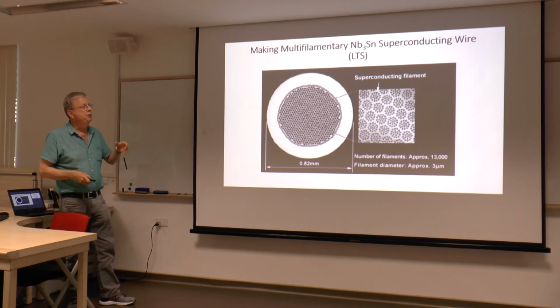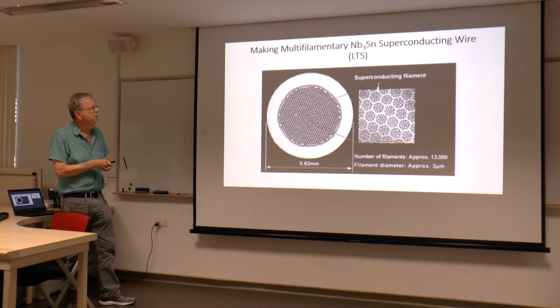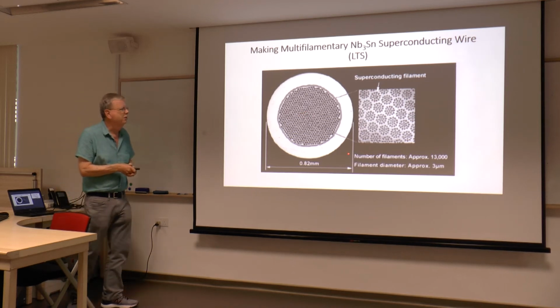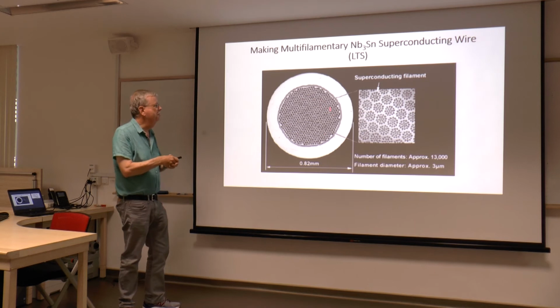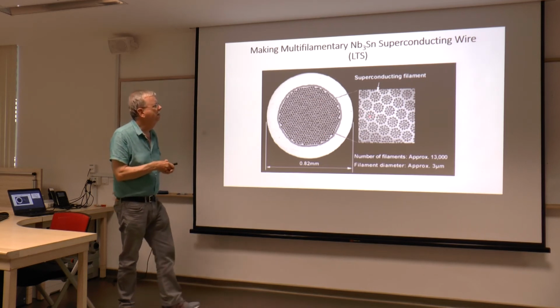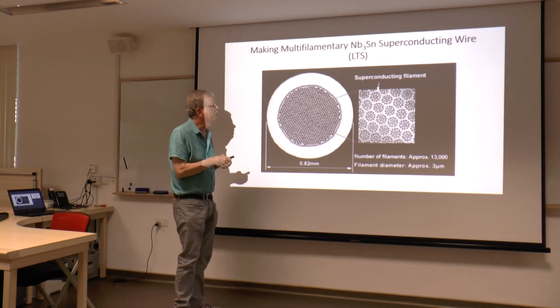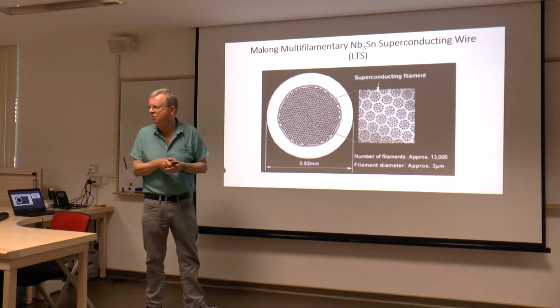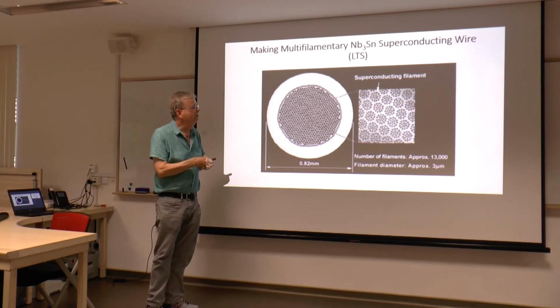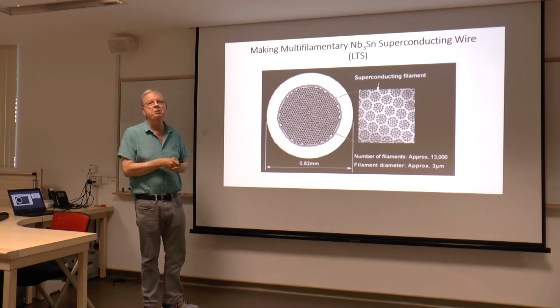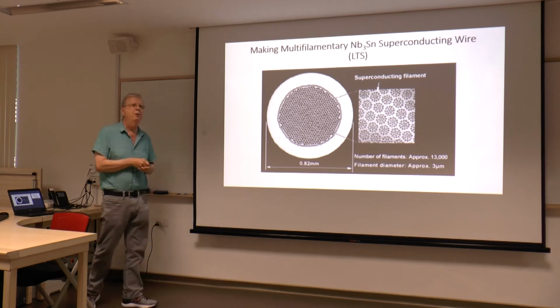So what they do is they draw niobium wire down in this rather complex geometry. This is just an expanded region here. So if you blow up these little things, that's these things. And so there's 13,000 filaments in this picture, and I once counted these. There's 20-some, I think. As soon as I say that, you'll correct me. But there's a lot of niobium wires here. And the niobium wires are in a bronze matrix. Bronze is copper and tin.